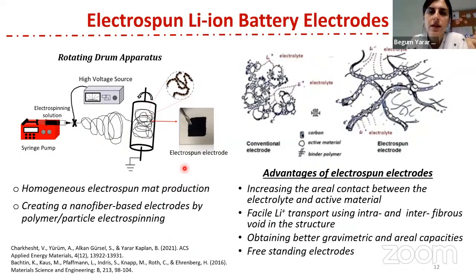We know these 3D electrode structures provide us higher areal contact between the electrolyte and the active material, as you can see here, and it provides easy lithium-ion transport using these intra- and interfibrous voids in the electrode structure, and it provides better gravimetric and areal capacity. And actually the most important advantage for me is the ability to obtain freestanding, flexible electrodes, and it eliminates the use of a current collector with this unique flexible structure.